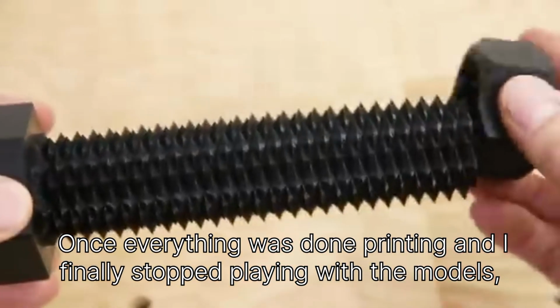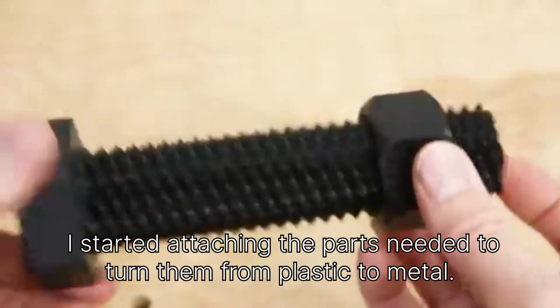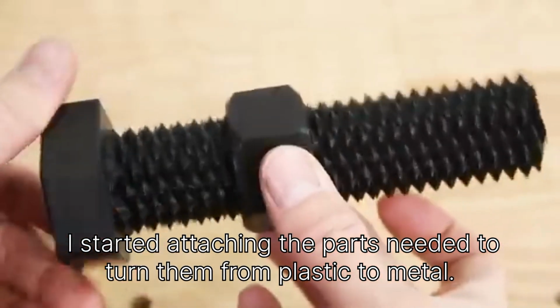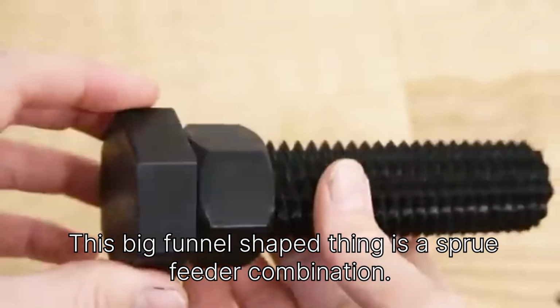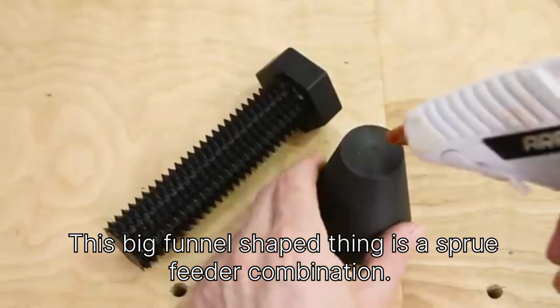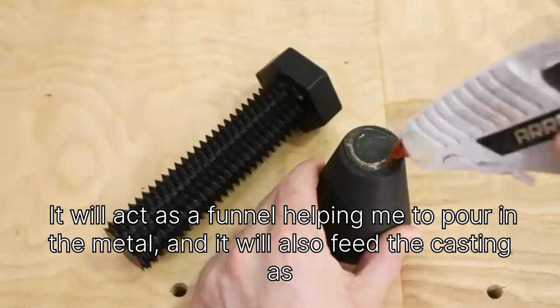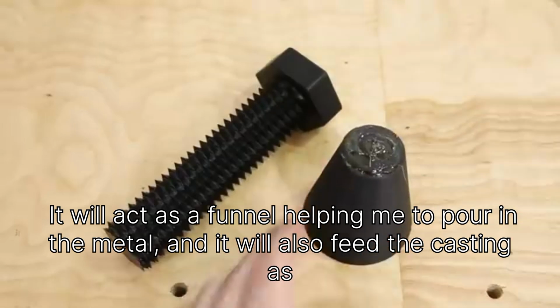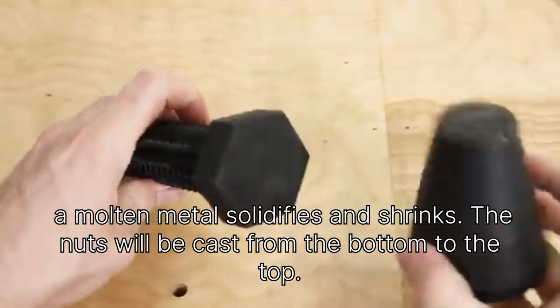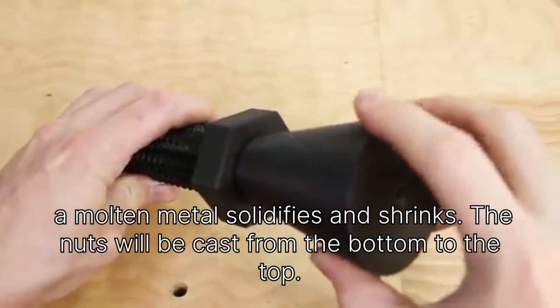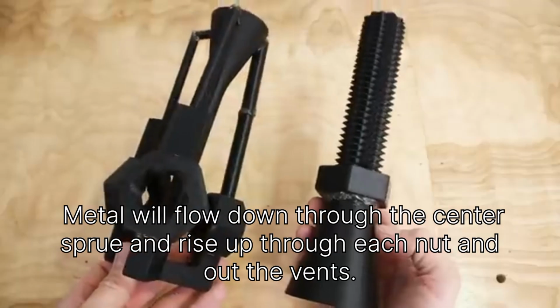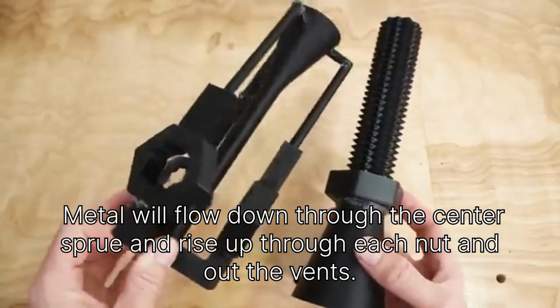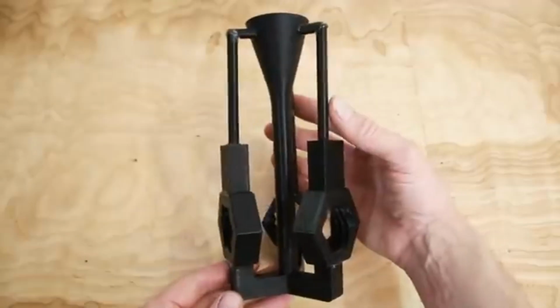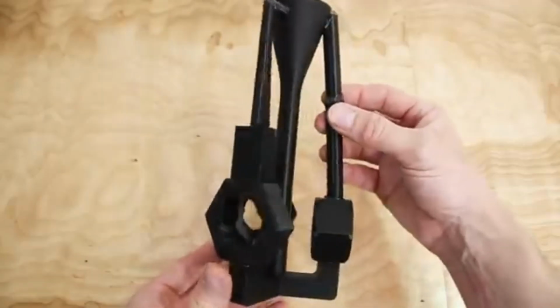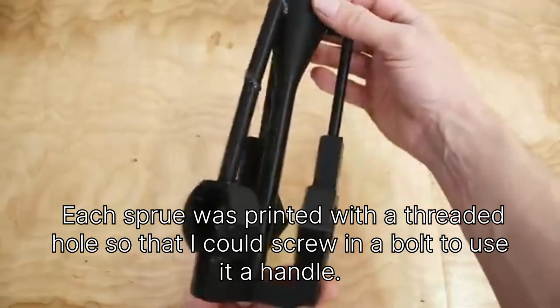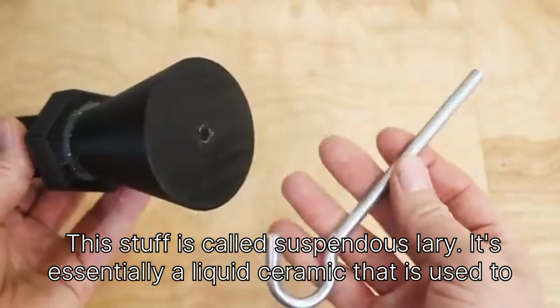Once everything was done printing and I finally stopped playing with the models, I started attaching the parts needed to turn them from plastic to metal. This big funnel-shaped thing is a sprue-feeder combination. It'll act as a funnel, helping me to pour in the metal, and it'll also feed the casting as the molten metal solidifies and shrinks. The nuts will be cast from the bottom to the top. Metal will flow down through the center sprue and rise up through each nut and out the vents. Each sprue was printed with a threaded hole so that I could screw in a bolt to use as a handle.